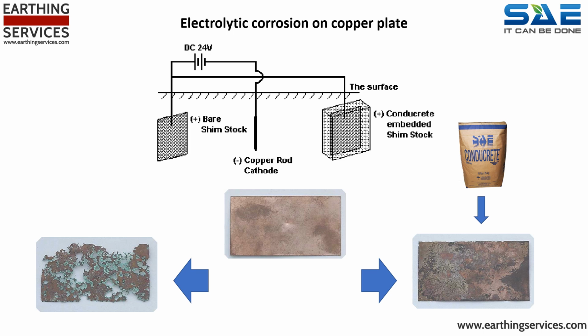The plate encased in Conducrete only has surface scarring that occurs during the binding process. The rate of electrolytic loss is substantially slower on Conducrete than it is on bare metal, which results in a future-proofed conductor. If the bare plate had been a lattice, then there will be substantially less material present, so deterioration will be an even worse prospect. Any item now reliant on the now deteriorated plate would be at risk in the event of a fault that it can no longer manage, as would anyone in the vicinity of it. Remember, electrolytic discharges are unavoidable, and even adjacent discharges from other systems can badly affect a given system.